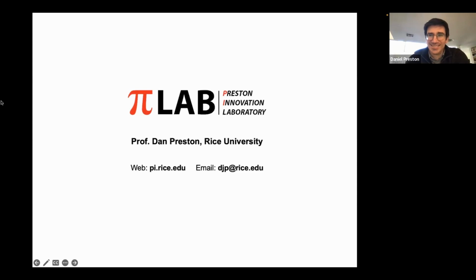Hi, Patty. Hey. So I think it's interesting with this higher temperature and especially that you use IR imaging. When we did experiments with droplet impact on hot surfaces, so we heated the surface, not the water, after a certain amount of time, we also saw a degradation. And that happened with surfaces that were on the order of 60 to 80 degrees Celsius. So I saw in one of your slides, you went up to 600 seconds, so 10 minutes. Whether you do see over time, because if you have the insulation, you should over time accumulate more heat, right, on your sample. So technically your sample should get hotter than on a super hydrophobic surface without your insulating layer. So I wonder how steady state compatible this surface actually is.